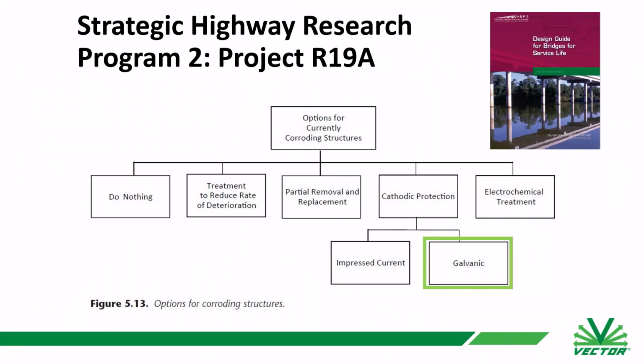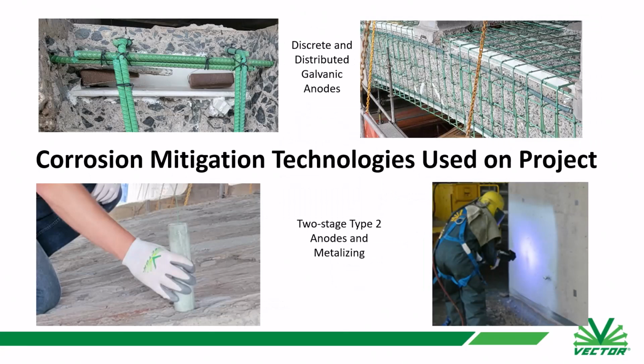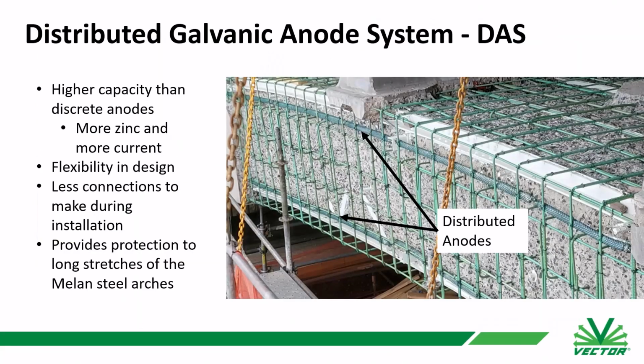So from a corrosion protection standpoint, in addition to the repairs, how do you get this structure to last for the 50 years? Because the repairs themselves aren't going to really solve the issue. And so there's a number of different techniques that were utilized, and I'll talk a little bit about these. So here you see the original steel. It's been coated with a protective coating where it's been exposed. And then they also used new steel around that, because there's no rebar in this structure. It's just the steel angles.